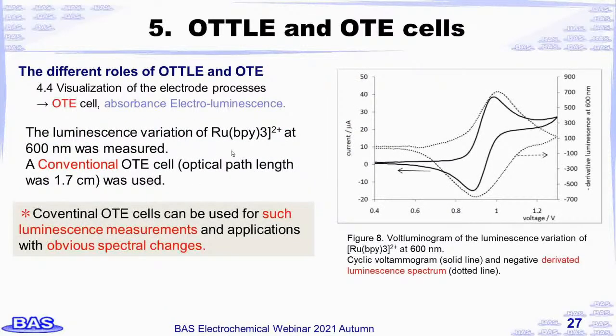The luminescence variation of tris bipyridine ruthenium at 600 nanometers was measured. A conventional OTE cell was used. Conventional OTE cells can be used for such luminescence measurements and applications with obvious spectral changes.